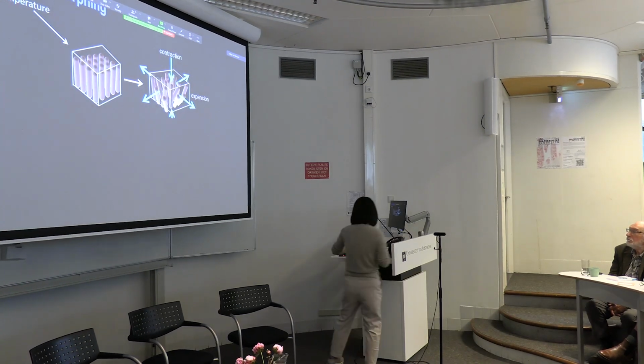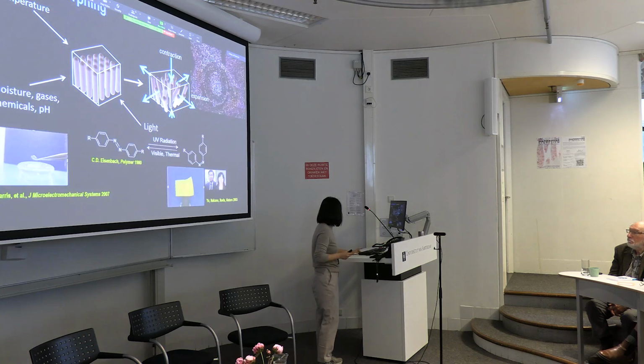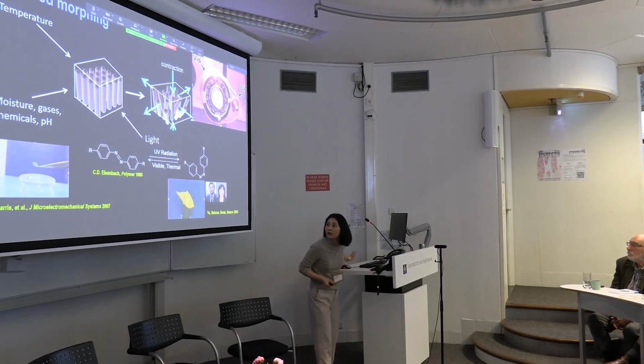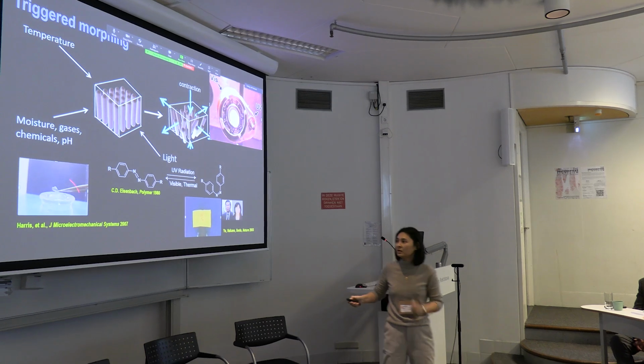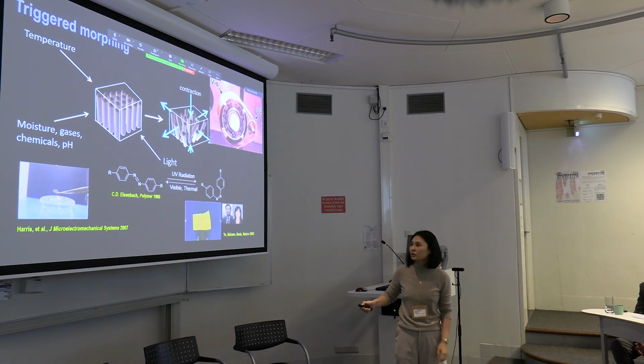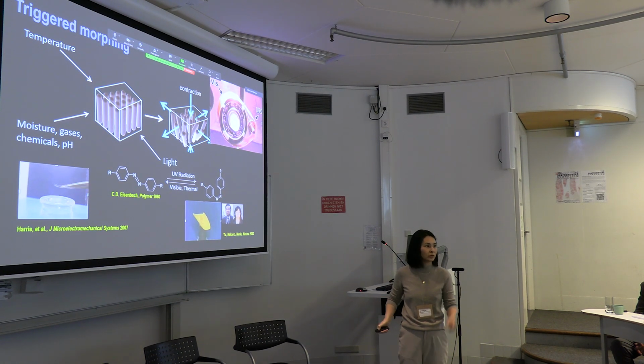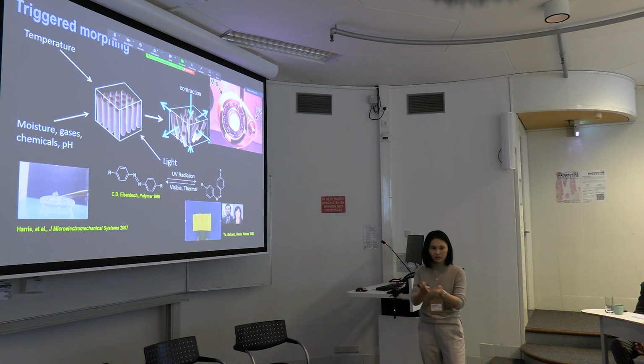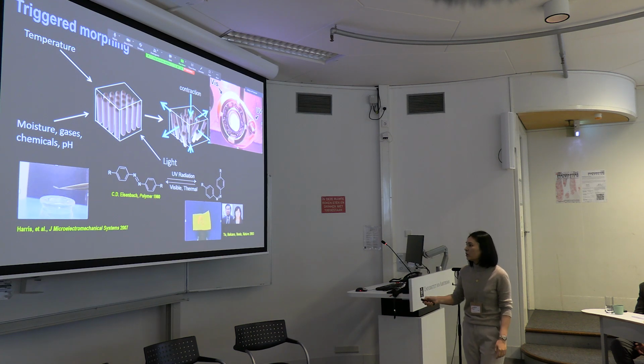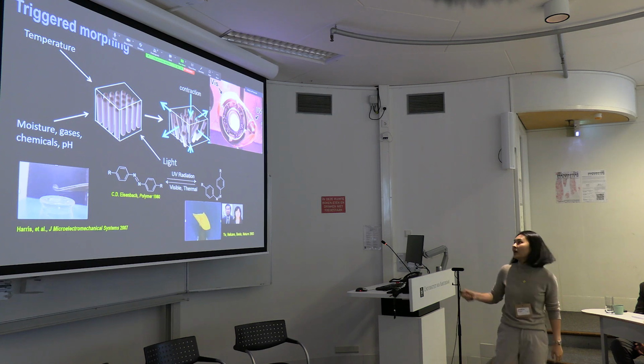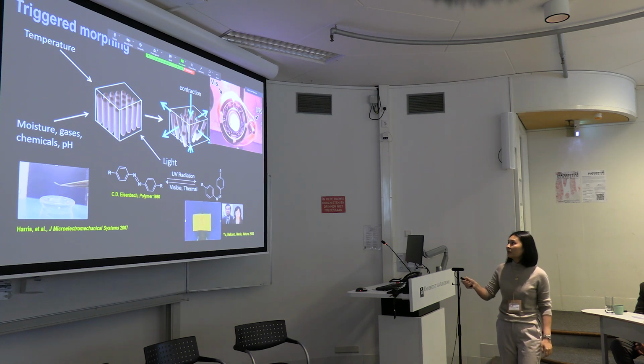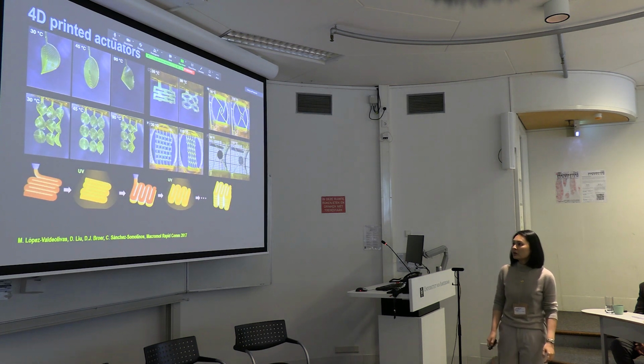And of course, with that we can go further. For example, we can make the bending respond to humidity. What you see here is the film close to the water bath, so the humidity is higher, the same bending, same molecule alignment. We can also make this respond to light. And then eventually, for example, you can connect this material to a wheel, and as a belt, the expansion and the shrinkage can eventually rotate this wheel to realize certain functions.